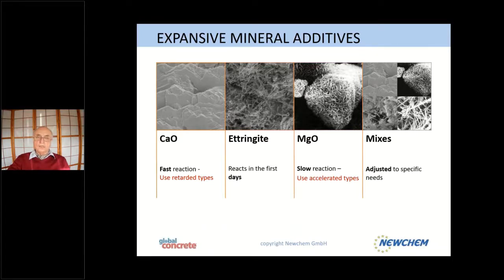So what you see here is a particle of magnesium oxide, and you see the crystal of the magnesium hydroxide growing on the surface. It is not a process which is going through a dissolution of the particles. We have now changed the calcining conditions so that the magnesium oxide is accelerated, and we can guarantee that in 90 days underwater, the whole magnesium oxide is completely reacted. We can make mixes now also, because depending on your application or the customer's application, people want to have faster or slower reactions. And with these 3 systems, we can play a nice tune on the piano.